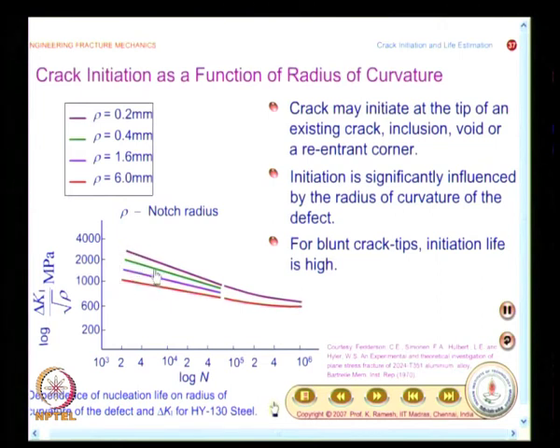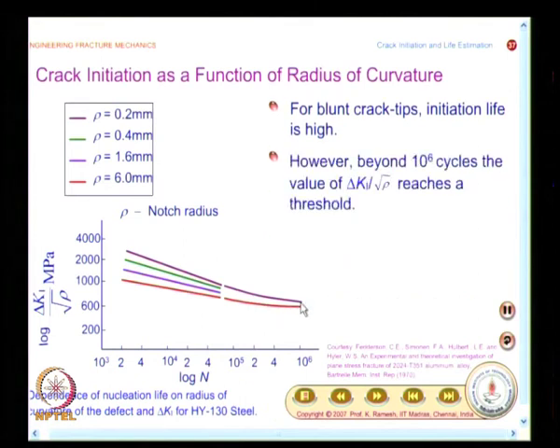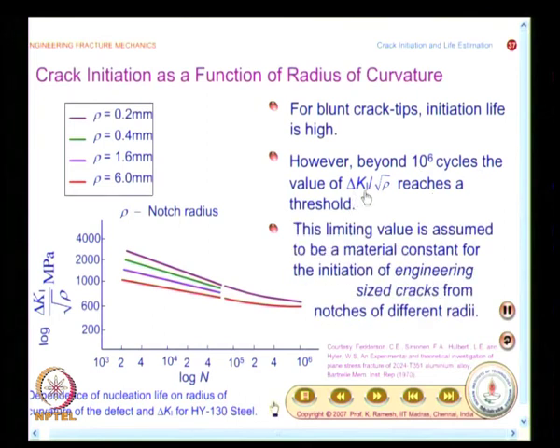And you find when the radius of curvature is higher, which is indicated by blunt crack tips, initiation life is high. It takes a longer time to get initiated. And you also have this as a material property. Beyond 10 power 6 cycles, the value of delta K 1 divided by root of rho reaches a threshold. That is what you see here. The main purpose of this graph is to show that delta K 1 divided by root of rho reaches a threshold. And people have found that this limiting value is assumed to be a material constant for the initiation of engineering sized cracks from notches of different radii. So, people call this the initiation fracture toughness.